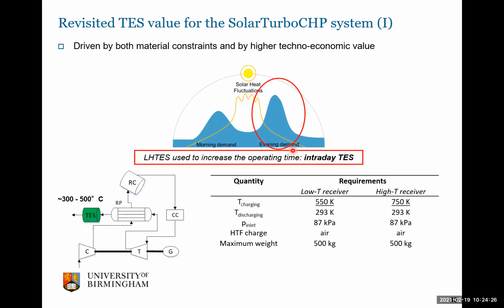So from a shorter duration storage for fluctuations, we moved to slightly longer duration storage for intraday storage of heat, for provision of heat to the customer at the end point of application. Depending on the couple of different configurations of the upstream process, we had a couple of different possibilities. Depending on the receiver configuration, an application at around 300 degrees C and another one around 500 degrees C. And this obviously still remains in the domain of what I would define as high temperature thermal storage. It opens certainly many more opportunities for material selection and design of the component.